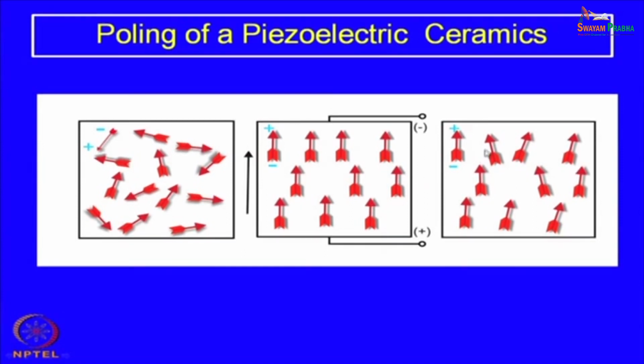However, if you remove the applied voltage, then there will be a little bit of readjustment, a slight misalignment, but it still remains more or less aligned. Now, that depends on the remnant polarization. If the remnant polarization is very high, then this will be retained. If the value of the remnant polarization is not that high, then it may change over to its original position very quickly. So, in piezoelectric materials, mostly the remnant polarization is quite high, and therefore, even after the removal of the applied field, the dipoles tend to remain oriented in the direction of the applied field which was applied for the poling.